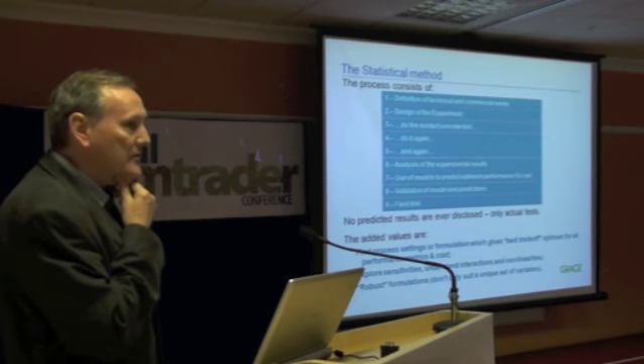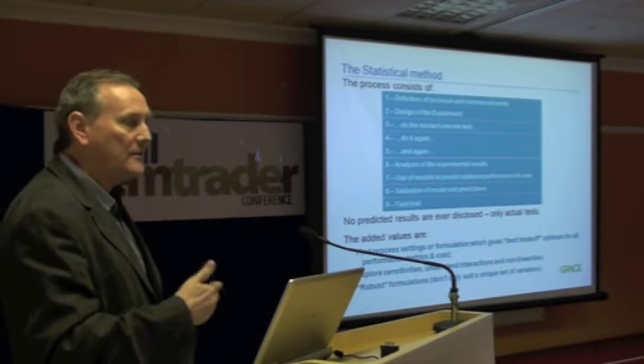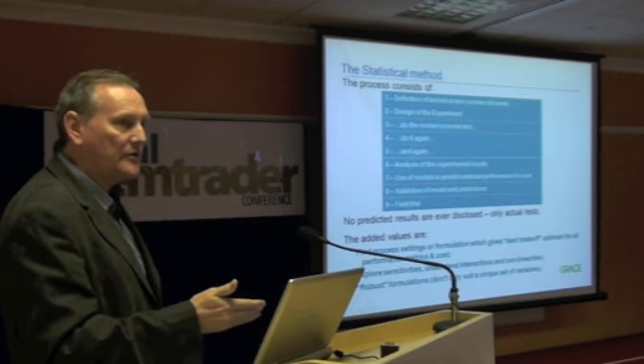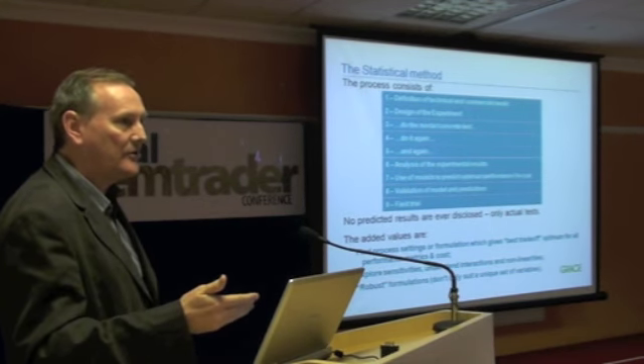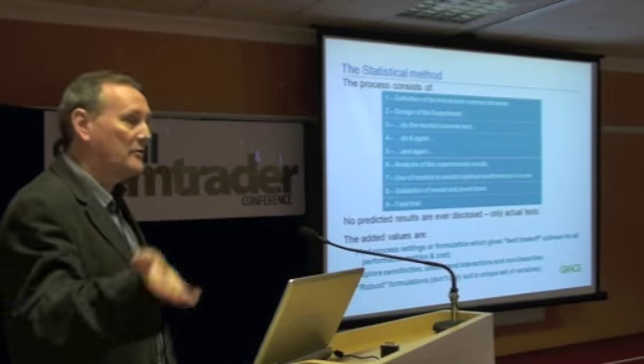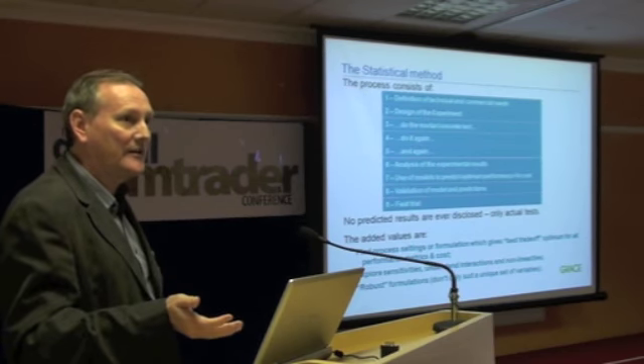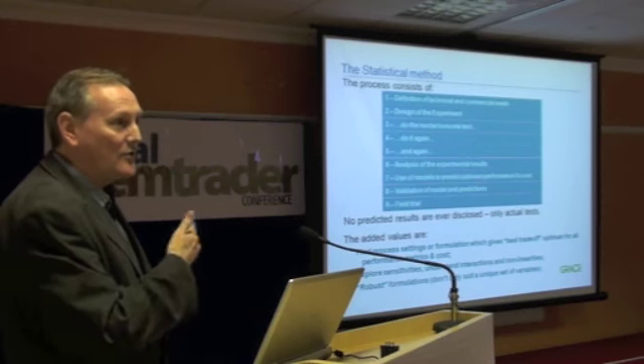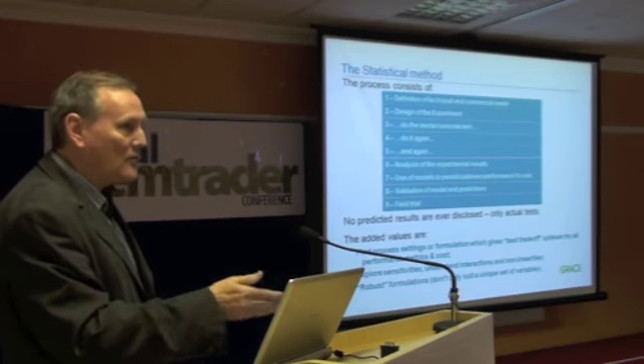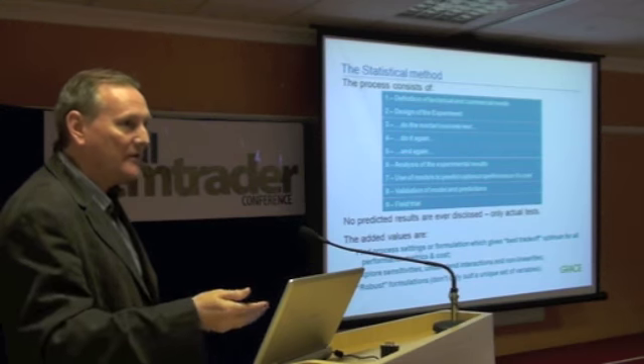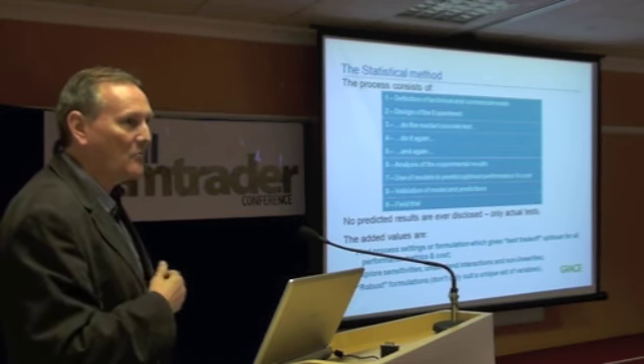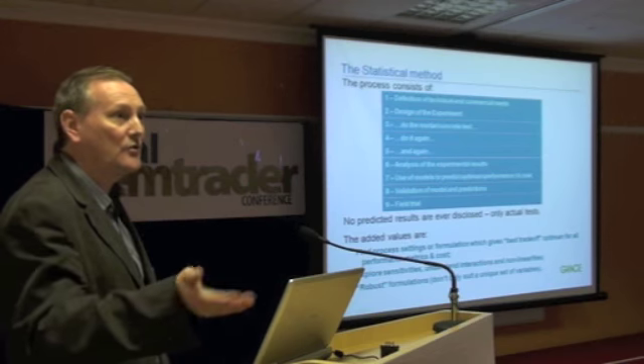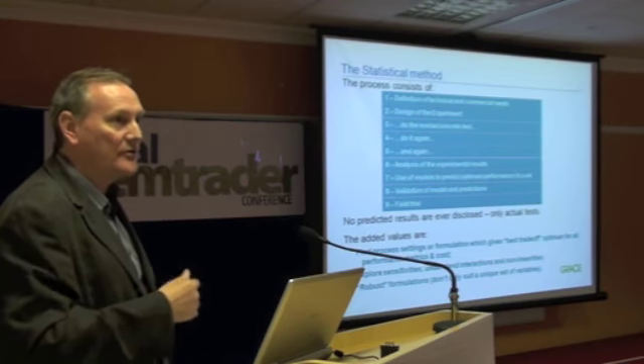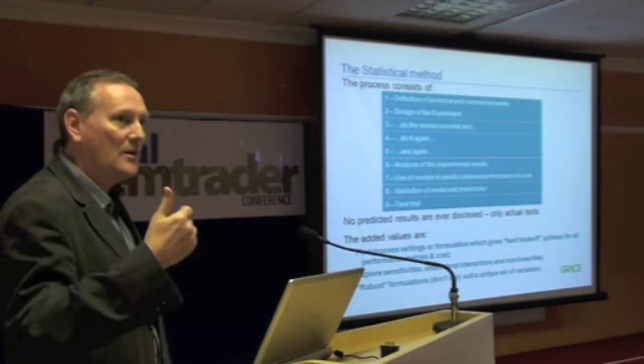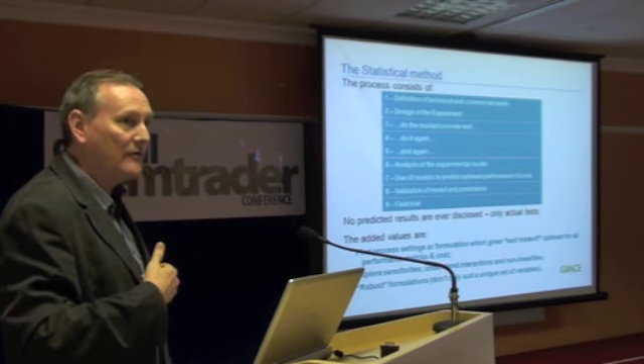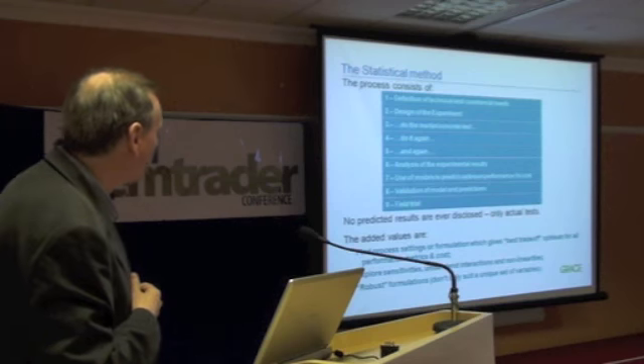And what that means is you have a pre-screening set of tests, you then have the main customization set of tests, and then you have the verification tests. And guess what? We're in the field all of you guys are working in, waiting for 28 days at least. So you're doing a round of tests, plus a bit of organising time, repeating. So it's taking about 5 months to customise one product. So we don't do it lightly. We're not going to do it for a $10,000 opportunity. It's for big cement plants, big producers, where there's value for us, and it's worthwhile doing for the cement plant.